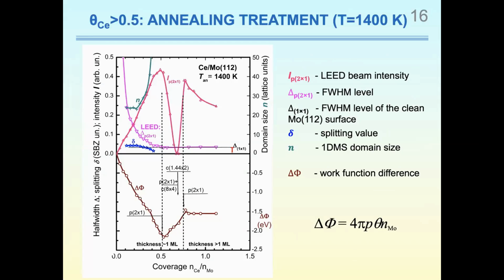Well, let me ask a short question about the dipole-dipole interactions. In work function, you talk about the energy needed to extract an electron from the Fermi level to the vacuum level, yeah? By depositing cerium on the surface of molybdenum, you are saying that cerium has a lower work function than the molybdenum. This is why you have minus 2 electron volts, for example, for the coverage of 0.5. Is this my understanding?